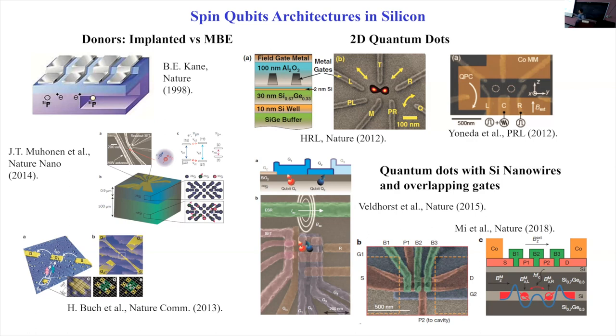Okay. And more recently, people also came up with ways of using silicon nanowires and then growing so-called overlapping gates, because silicon does have larger effective mass compared to gallium arsenide. So when you try to grow a quantum dot with large enough orbital excitation energy, you have to make the quantum dot smaller than in gallium arsenide. Okay, and using the 2D structure is a little harder to do that.